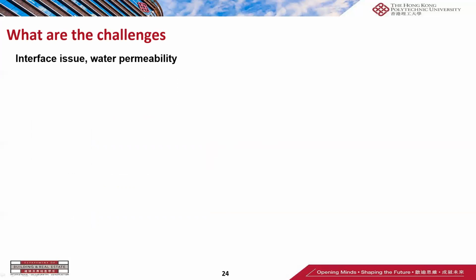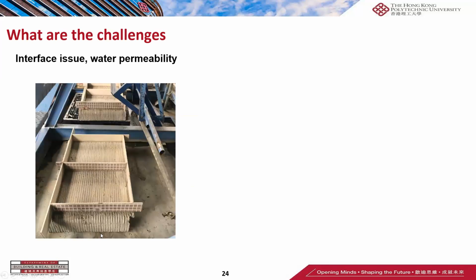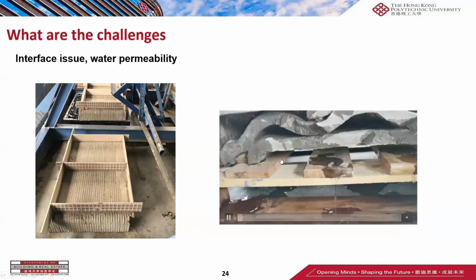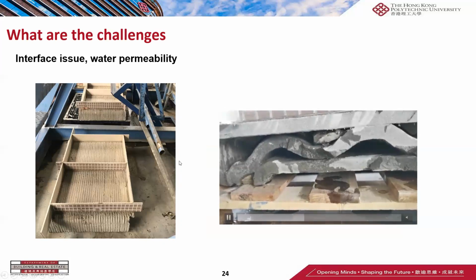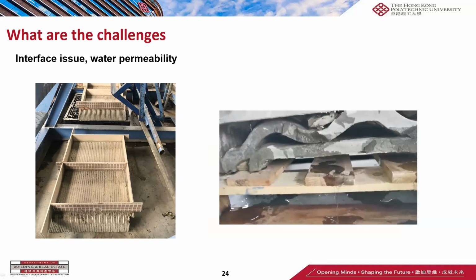We know that the concrete printing process is a layer-atop-layer manner. Because of this unique construction process, the weak interface may be a big challenge for this technique. Just like this, this is a 3D printed concrete wall. Then we use tiles to form this kind of water pool, just like this. Then the water will be poured in this area. So in the test, you can find that the water can directly penetrate through this concrete wall system. This is mainly because of the weak interface in the printed structure.